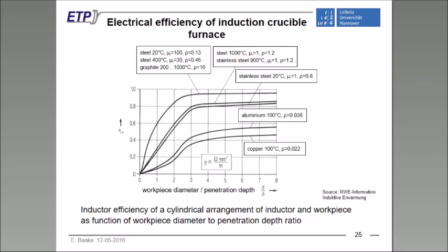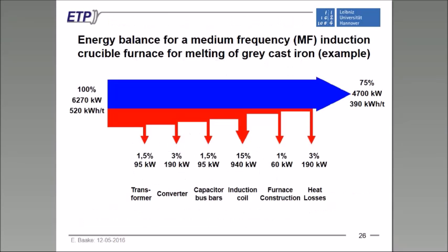And that's the second reason why medium frequency furnaces, several hundred hertz, are used today instead of line frequencies: in order to get a higher efficiency when we want to melt very small size scrap, when we want to start with the empty furnace filled up with small size scrap and use the so-called batch process, not the process with the yield which was used in former times. This is the second reason for this.